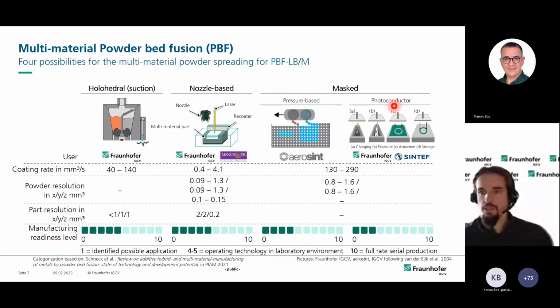And then you've got the system with the photoconductor. Photoconductor sounds very fancy, but actually it's what you find in all of your laser printers. You've got a photoconductor which is charged, then exposed to light, then the charging is removed at the places where you want it removed, and then you can attract your powder to the contour and place it onto the build plate.